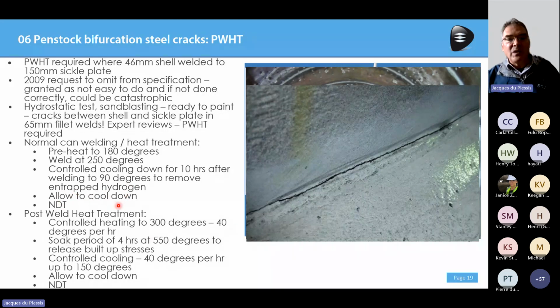Now, with post-weld heat treatment, in addition to this, that weld was heated up again to 300 degrees at a certain rate of 40 degrees per hour. Then it was soaked for 4 hours at 550 degrees. You can see it was some massive exercise. And then there was a controlled cooling down again, and then it was allowed to cool down naturally, and then you do your final non-destructive testing. So major exercise, but in the end, it was required.